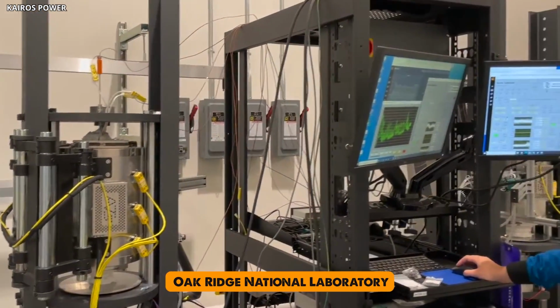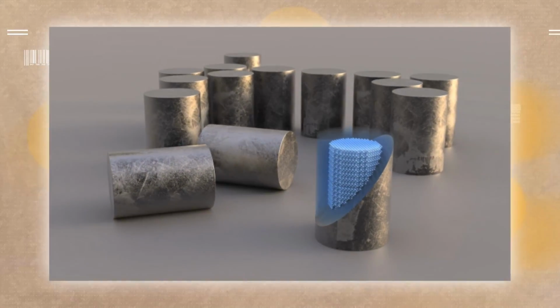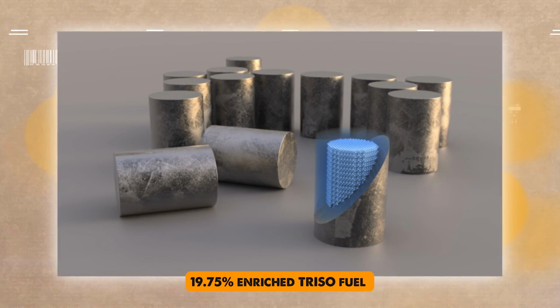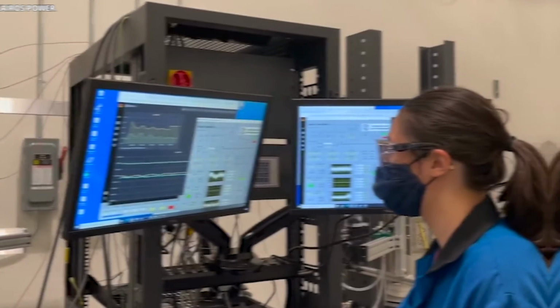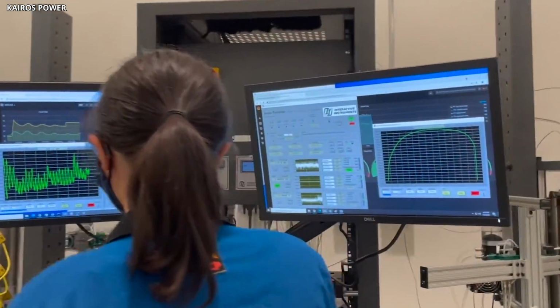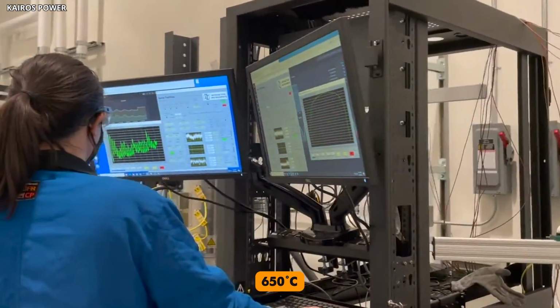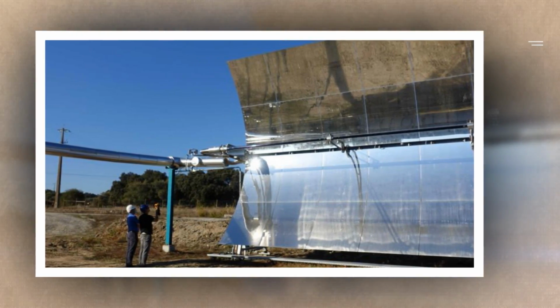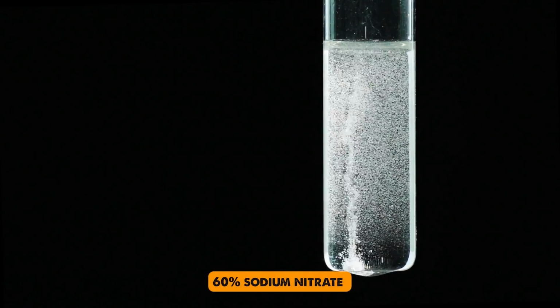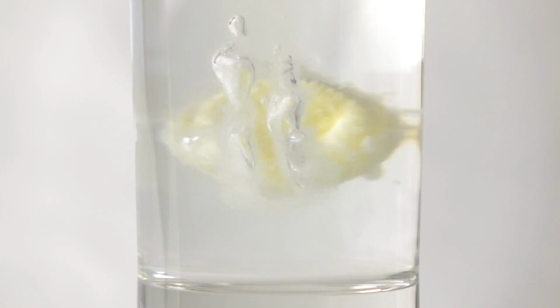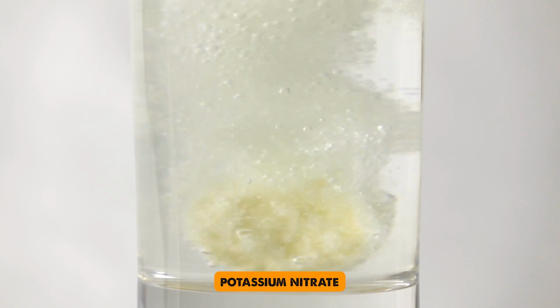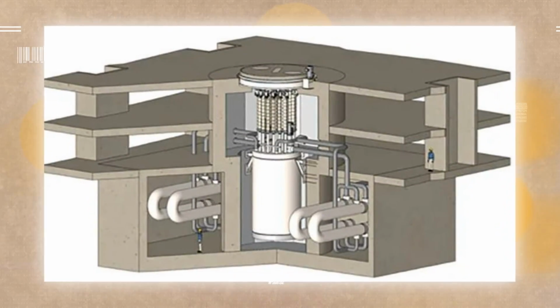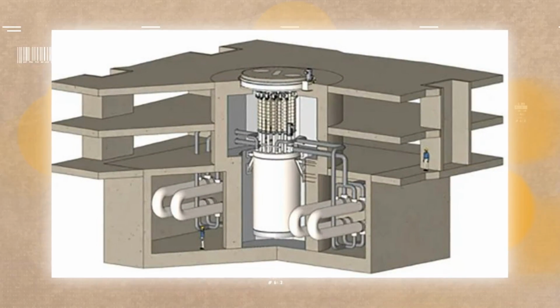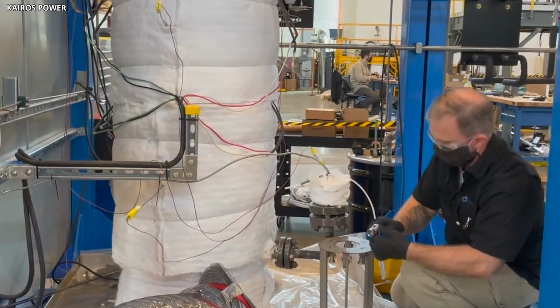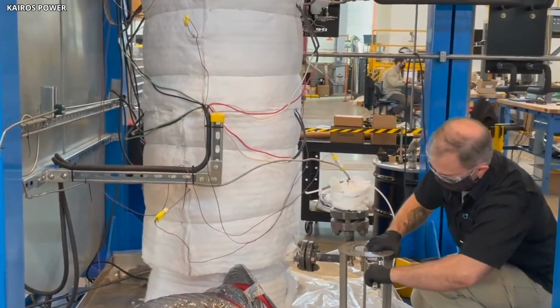Collaborating with Oak Ridge National Laboratory, the reactor will use 19.75% enriched triso fuel in pebble form, allowing the reactor active refueling and operating at temperatures up to 650 degrees Celsius. There's a secondary circuit that utilizes a solar nitrate salt mixture, which is composed of 60% sodium nitrate and 40% potassium nitrate for a steam generator. One important detail to know about this reactor is that it has a reliable safety profile and that it contains passive shutdown if things ever go out of hand.